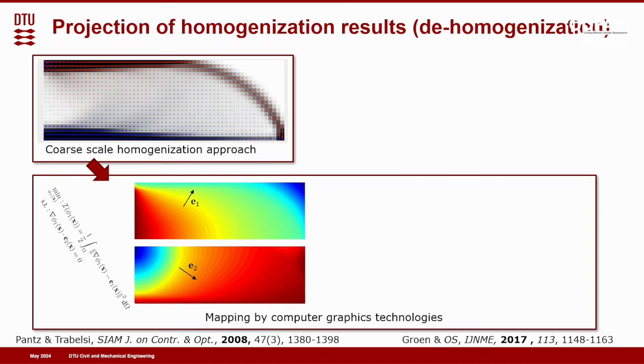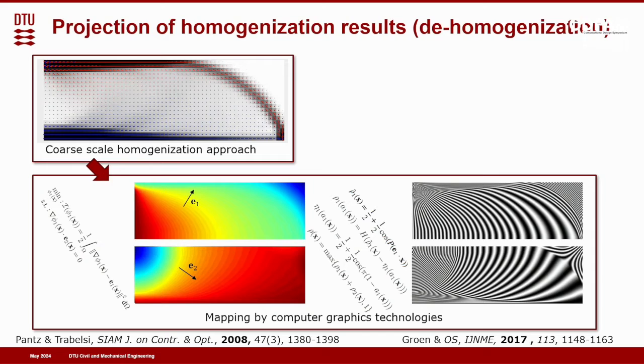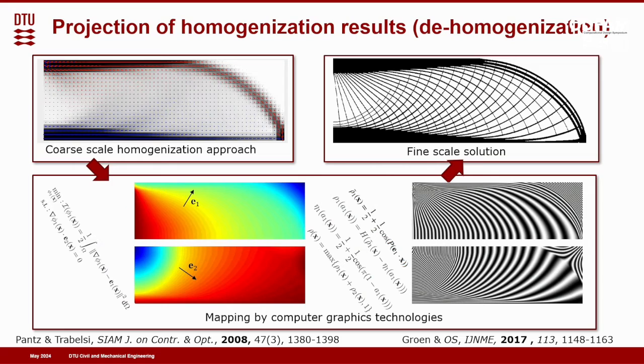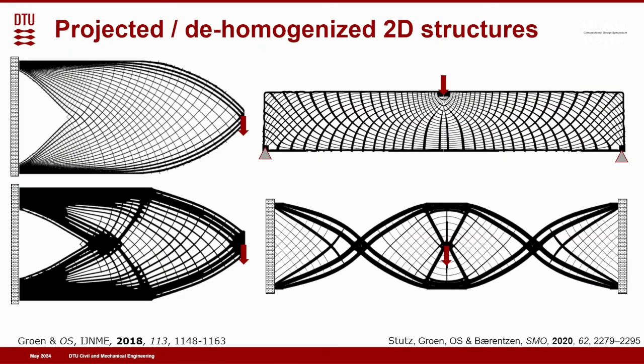Then if we take cosines of these fields there, we get these nice zebra patterns. And then if we take those 2 zebra patterns and reintroduce the lamination thicknesses and put them together, then we get these beautiful and highly optimal structures. They're close to the theoretical optimum. And the nice thing is that compared to a similar topology optimization procedure, we gain something between 100 and 1,000 in CPU speed up. So this is an extremely efficient method, and I can show you lots of pictures.